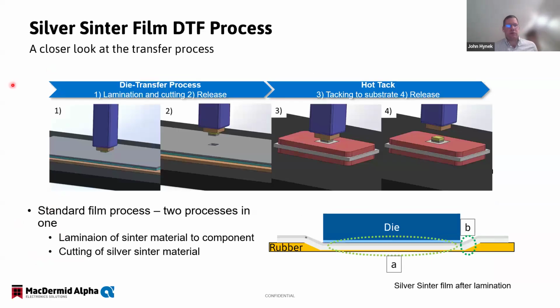Here we go. So let's take a little closer look at the DTF process itself, just the process of actually getting the silver sinter material onto the back of the die. The first thing you're going to do is take your die and heat it up on the bond head. Then you're going to take the bond head and place it into the silver sinter film, at which point the silver sinter film will be separated from the bulk film and just put onto the back of the die. You can see here a much more in-depth look at what's actually happening.